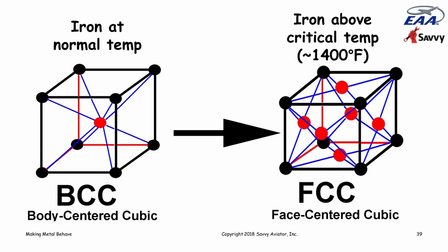If we heat iron up to a high enough temperature, what's called a critical temperature, it's about 1400 degrees Fahrenheit, which just happens to be about the temperature that causes it to glow cherry red, the crystalline structure of the iron magically changes to something called face-centered cubic, where instead of having a molecule of iron in the middle of the cube, we have a molecule of iron in each face of the cube. Face-centered cubic has very different characteristics than normal iron. It becomes non-magnetic, for example.